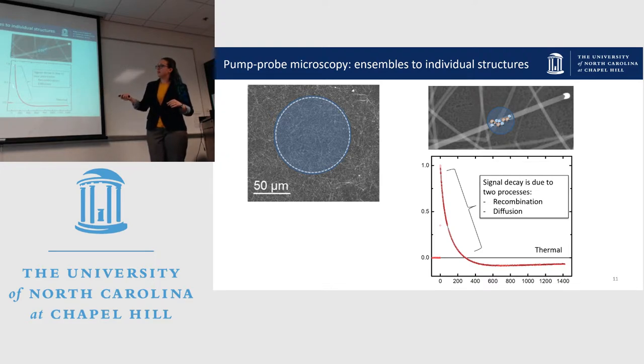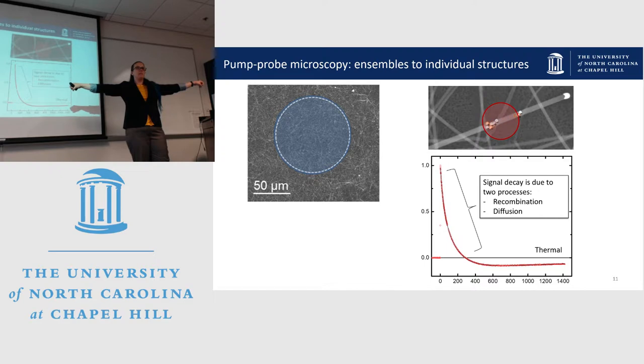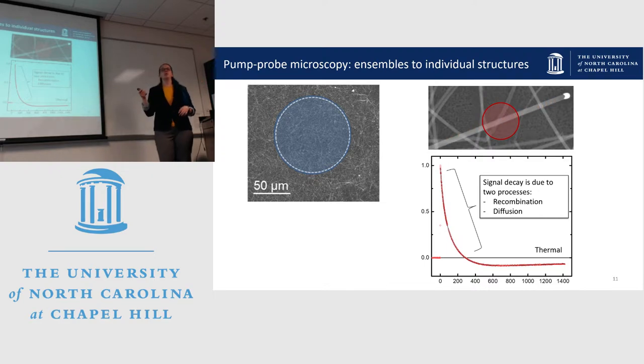With microscopy mode, it's a little bit more tricky, though, because now not only do you have a signal decay due to recombination of the carriers, but also to diffusion of the carriers outside the probe spot. What I mean is our pump excites a number of carriers in a very localized region of the wire. We probe it, and the carriers recombine with one another, but they also travel outside of the probe spot, right? So our lifetimes always look faster than they actually are.